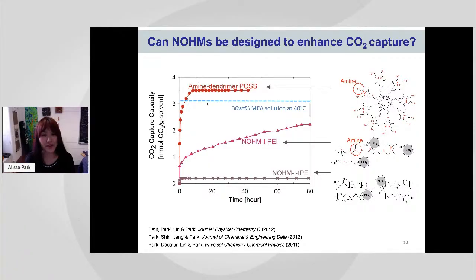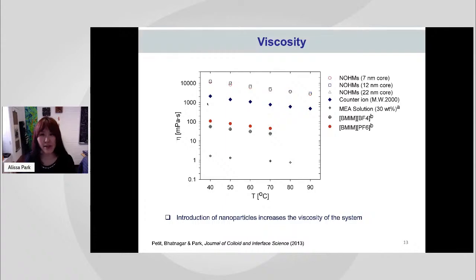So we started thinking about this quite a bit, and said, well, maybe the first thing is, since it's a liquid solvent, we should check the viscosity. And this is our viscosity data. If you look at the bottom, the cross data points are the MEA solution, which is a typical CO2 capture liquid solvent. Compared to that, the second group with the red dots are the ionic liquids. And the third group at the top are our NOHMs materials. So as you can see, NOHMs and ionic liquid have a significantly higher viscosity compared to a liquid solvent like amine. But also, if you look at the y-axis, this is a log plot.